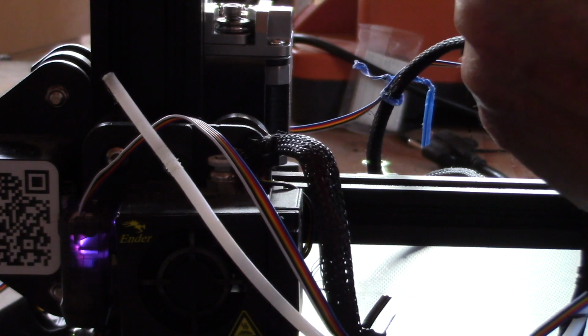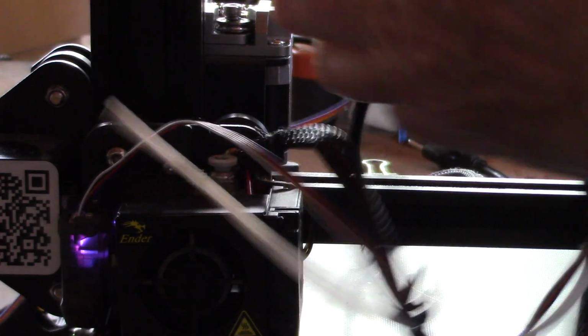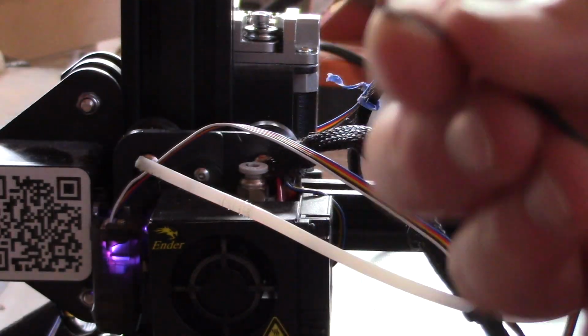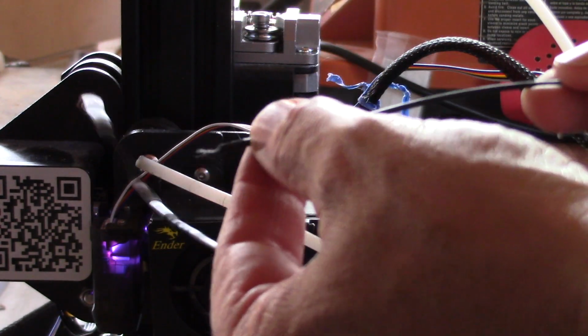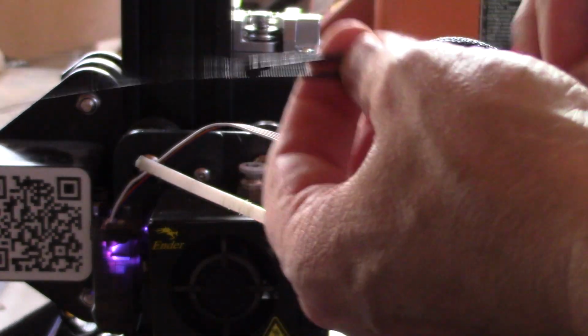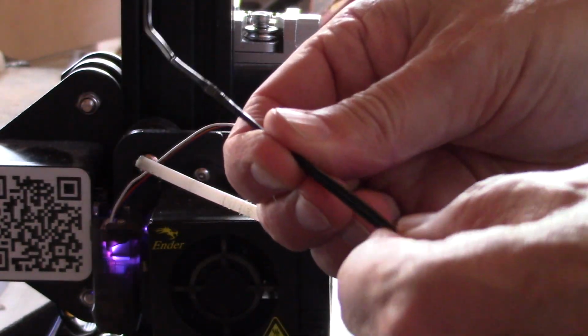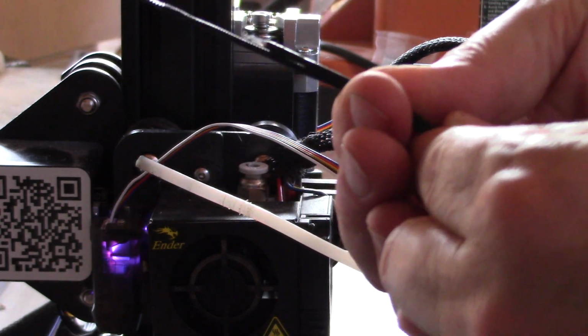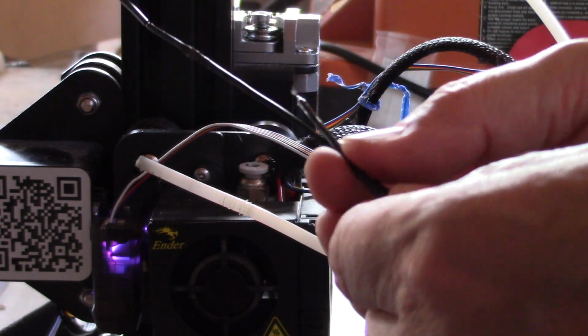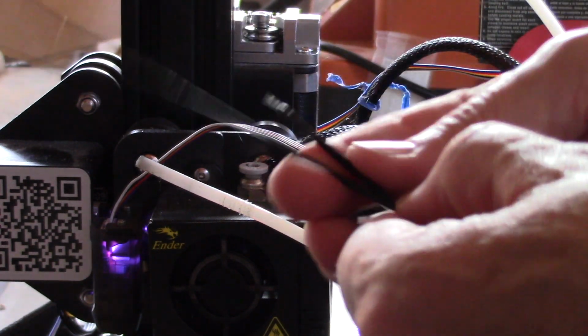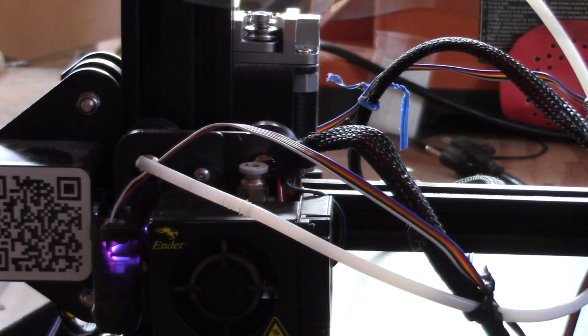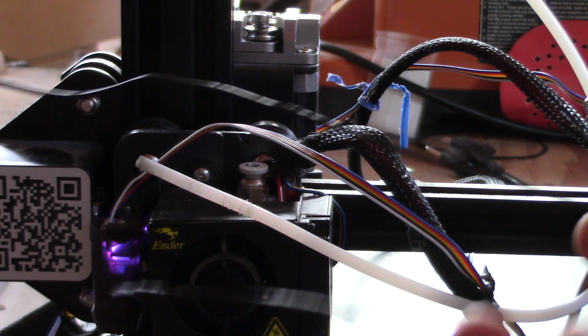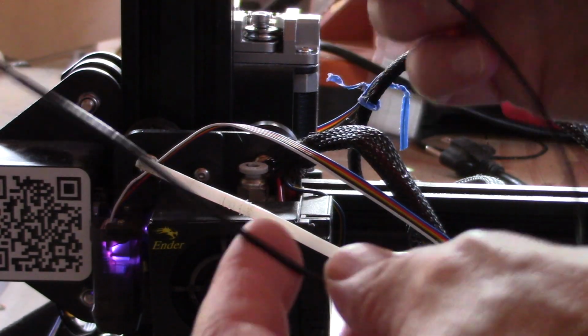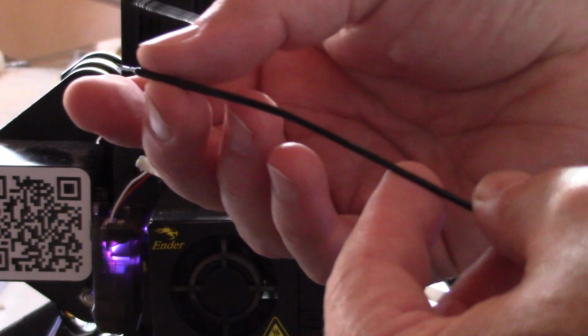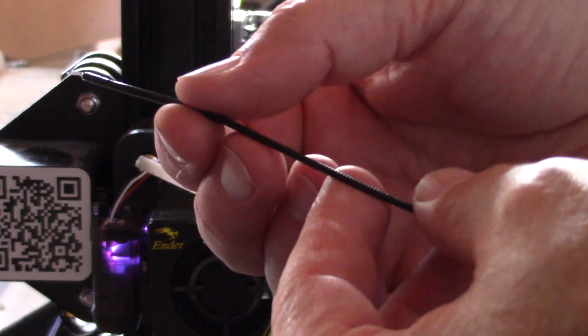All right. Oh boy, that's a big old jam in there. This is going to be really hard to see on camera, but the diameter here is quite a bit wider than it should be. Now, we're in a heat wave, and I mean it is hot. It's 111, and I'm inside a garage, so I imagine it's even hotter than that in here. And I think this got so hot that this filament became soft, and it started bunching up into the end and eventually just jammed it.